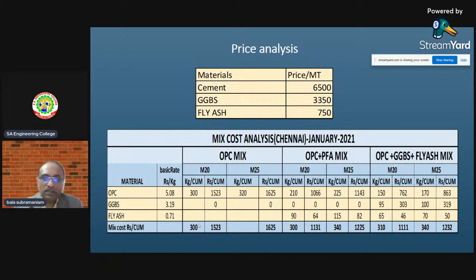So we are going to sell it to the customers who are using OPC, M20 and M25 grades. For M20 customers, it is 300 kg. The price comes to 1,523 rupees. Whereas for M25, they use 320 kg, because the increase of 20 kg will give you an additional 5 Newton per mm square. So for M25 customers, 320 kg of cement is used, and the price comes to 1,625. Now, this box is the OPC mix, and similarly, this is the PFA mix. Here, see the same mix.